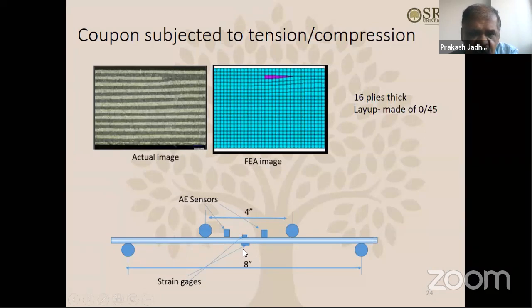What we have done is design the coupon in such a way that there is a ply drop near the surface. We can decide whether to put the ply drop near the surface which is under tension, or near the surface which is under compression. So that we can decide.